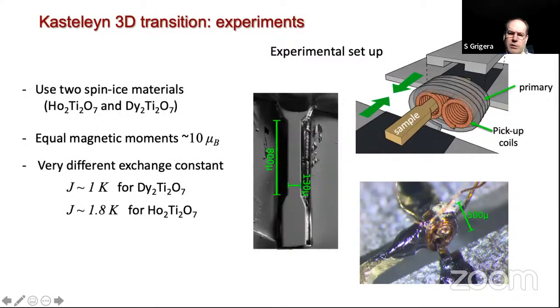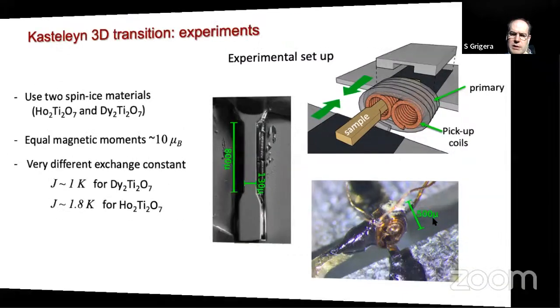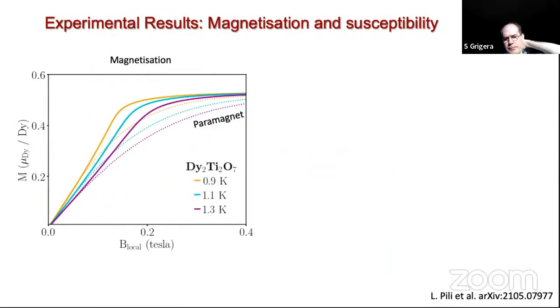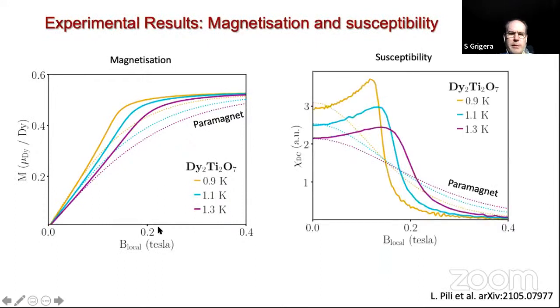So what we did was to cut samples. These are very small samples because we also want to strain them. We put them inside a coil that we wound manually around the sample, and we measured susceptibility, and we also measured magnetization using a SQUID. So this is how the experiments look. This is the magnetization, and this is the susceptibility. This is for dysprosium titanate, and you see that you get essentially something that looks like